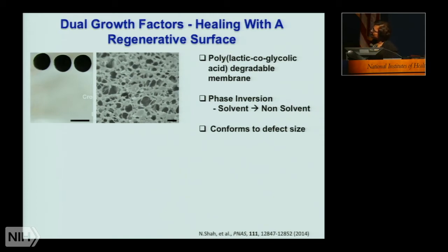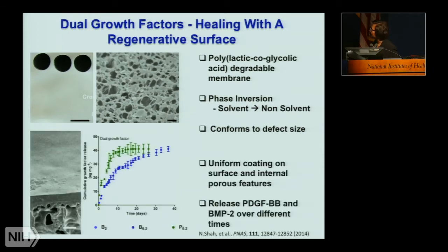And in this case, this was cut to the size of our cranial defect model. We then coated that PLGA, which degrades over a reasonable time frame of a couple of months, with a layer-by-layer film. And here, it's a little dark, but you can see that there's a layer-by-layer film sitting on top of this porous substrate. We can then allow release of the growth factor based on what we've done to incorporate the material. And in this particular example, we built BMP2 containing layers on the bottom and PDGF containing layers on the top. If you remember, PDGF is going to help support vascularization.